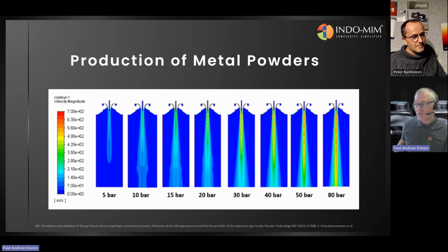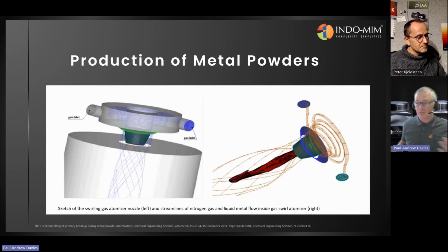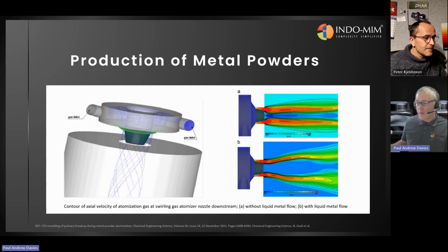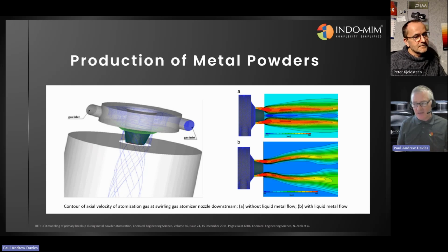But then you can, of course, adjust the geometries of the atomizer. And one obvious thing to do, perhaps, or not so obvious, is to include a bit of swirl, a bit of angular momentum to the atomizing gas, and that can have an interesting effect on how the gas interacts with the molten material. So you can see here the gas flowing through the atomizer and the molten material coming out, and with and without the metal flowing can have an influence on the gas flows, and that's very important. So often in gas atomizing the challenge is getting the atomization to start, and then generally it becomes stable, and you can even listen to atomizers literally to see how stable they are, and provide a bit of feedback loop on that as well.